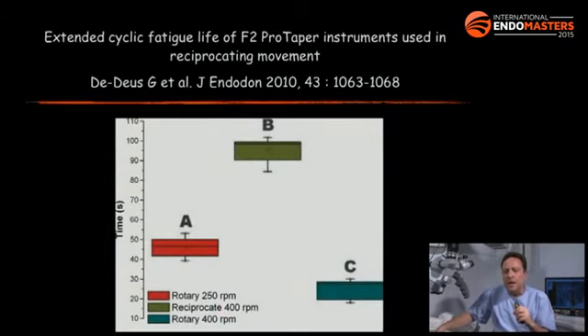And what you can see in this study is that if you rotate the file at 400 RPM, it will break in less than 30 seconds. If you rotate the Finishing File 2 at 250 RPM, it will last up to 50 seconds. If you reciprocate the Finishing File 2, you go up to 100 seconds, so almost at least 100% more. So you can see here that reciprocation is much safer in terms of cyclic fatigue than rotation.